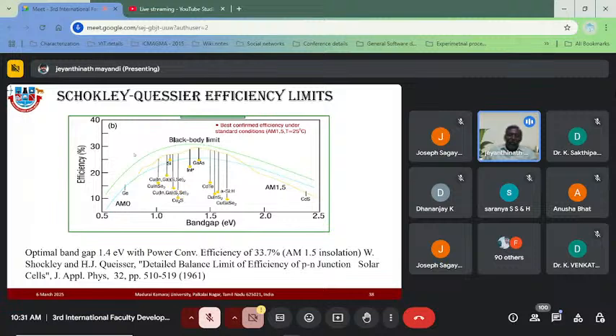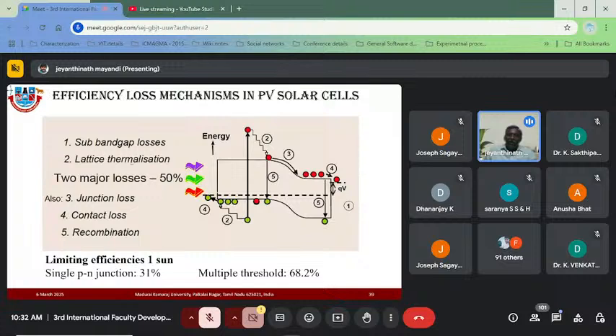And there are some limitations for this solar cell efficiency. You could see the silicon can go up to a maximum of 29%, and this is called the Shockley-Queisser efficiency limit. And for the other materials, you can see the theoretical limitations for AM 1.5 at 25 degrees C, you can have only so high efficiency, and depending on the band gaps, you could have different efficiency percentages. And the efficiency loss mechanism in a solar PV cell is given here, and these two are the major losses.